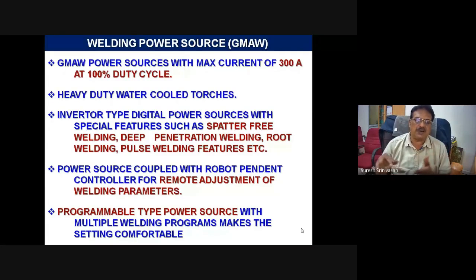So these features are to be built in your power source. And when you do root welding, please remember, when you set up the two pipes or two members, the root is the most critical factor, where the root gap may vary before welding or even during welding. At that time, your power source has to be an intelligent kind of power source, which can take the feedback and give the correction then and there within a split microsecond. So all these features are available with only digital type power sources, which respond within microseconds. Next level is pulse welding features, which help you to do root welding.